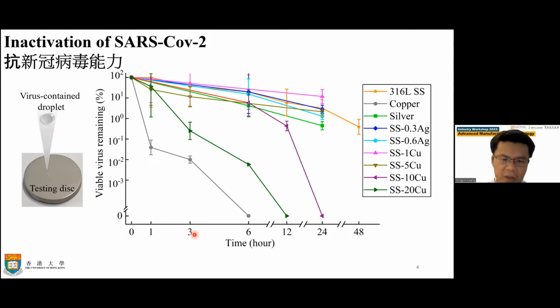So the amount of virus on the surface is reduced, and the possibility of being infected by this virus is lower. Less virus on the surface means the probability of infection is lower. So we consider stainless steel with 20% copper to have very good application potential for, say, lift buttons, because usually you clean lift buttons every 2 or 3 hours. Using our stainless steel, even if you don't clean, within 3 hours the amount of virus on the surface is already very low. This can help reduce the risk of transmission.